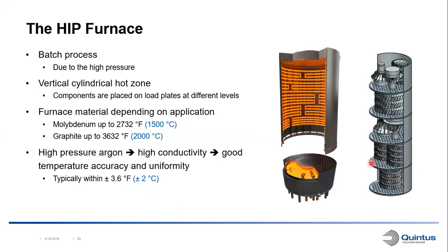There are some different furnace materials available depending on your application. So we have molybdenum furnaces that go up to 2700 Fahrenheit. These can process most metals with those temperatures. But then we also have graphite furnaces that go up to 3600 Fahrenheit for high temperature ceramics and refractory metals.